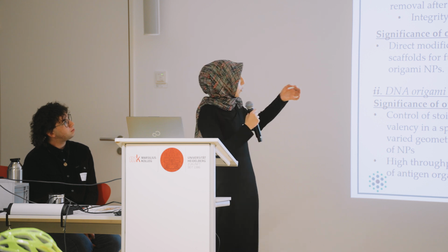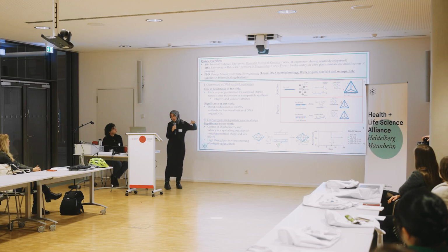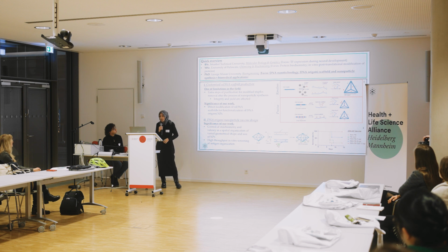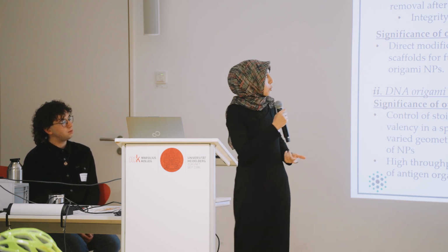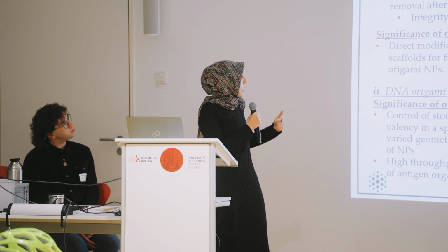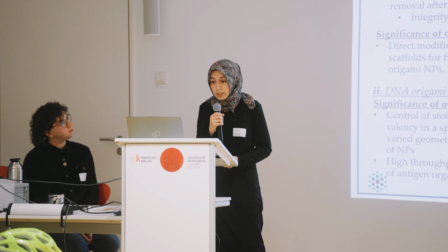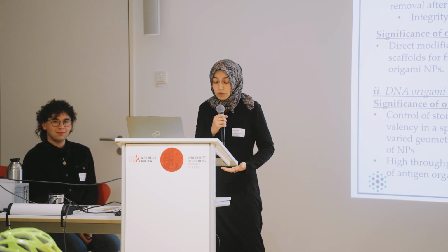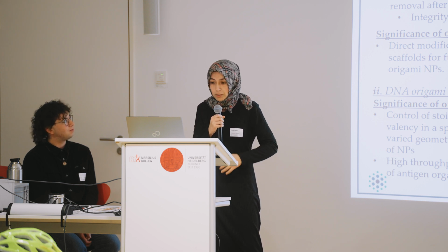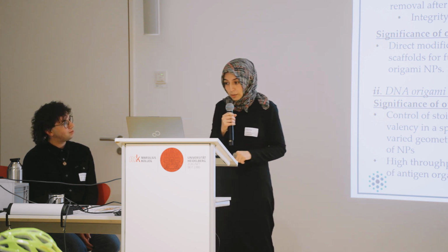Basically, I want to mention my main research, which is using DNA origami for vaccine design, but as a first step I wanted to show what I did first: generating a single-strand DNA scaffold. In DNA nanotechnology, people know that it's hard to generate your own scaffold for making nanoparticles for different purposes, because the main limitations of scaffold production are the extra steps of purification of modified staples before and after the process of nanoparticle synthesis. In the meantime, we achieved protecting the integrity and the yield of the nanoparticles after getting rid of the requirement for modified staples.